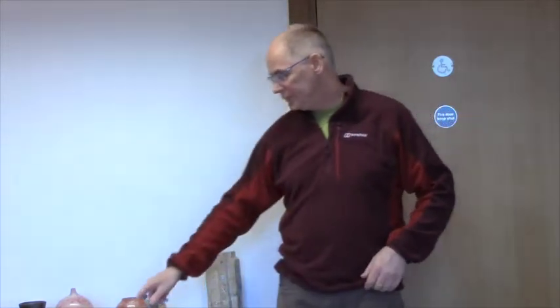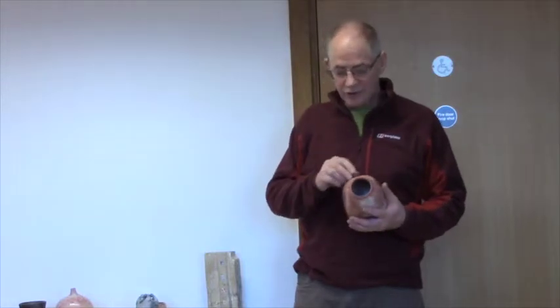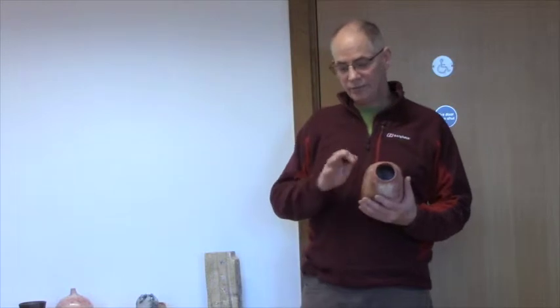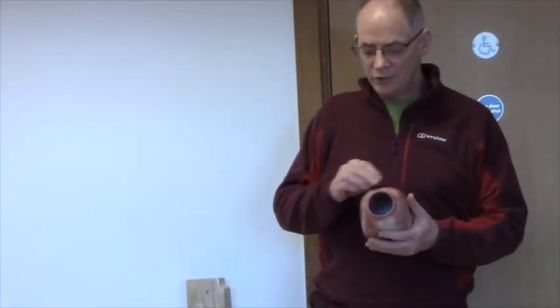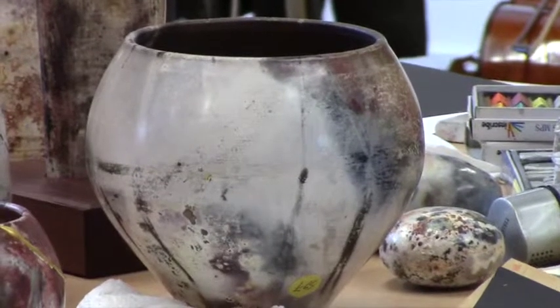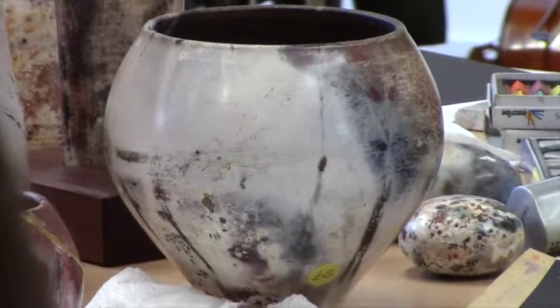And that's hours of work. This is my stone. This is the only stone that I can use. And I just sit there like that for hours as it's drying. So as it's getting to leather hard, you can do that. And it pushes the grog into the clay and leaves a fine film on the outside. You put it down, and as it dries, it goes matte again, so you pick it up and move on. I probably do the whole pot like that 5 or 6 times before it's bone dry. Then they're bisque fired in an electric kiln to 1,000 degrees.